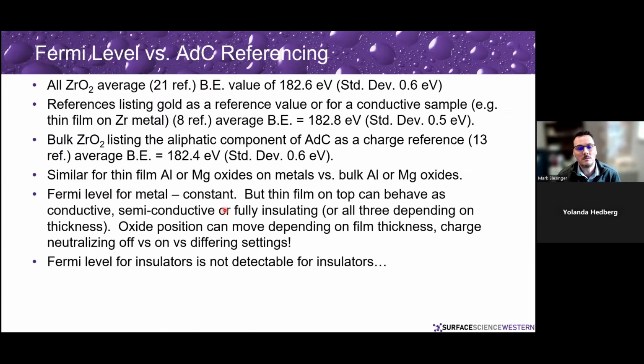And so you have to think about what you're analyzing. Are you looking at a thin film where you can do this kind of Fermi level referencing? Or are you looking at a bulk oxide? And those are the sorts of things that we look at. And so that's my rebuke to the fact that I keep seeing people say, "Oh, you can't use adventitious carbon. It's a no-no." They're wrong. In my opinion, they're just dead wrong, and in other people's opinion as well. But it has to be used correctly, and you have to understand it.